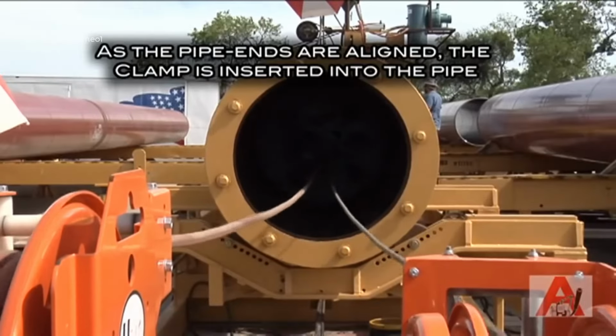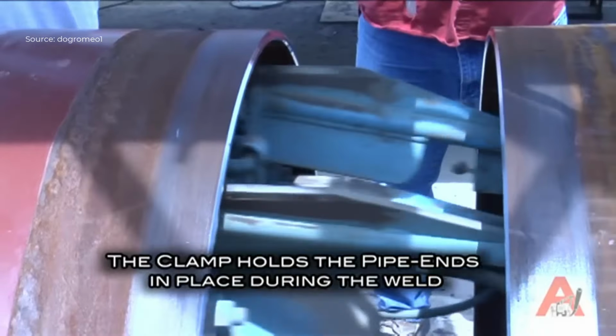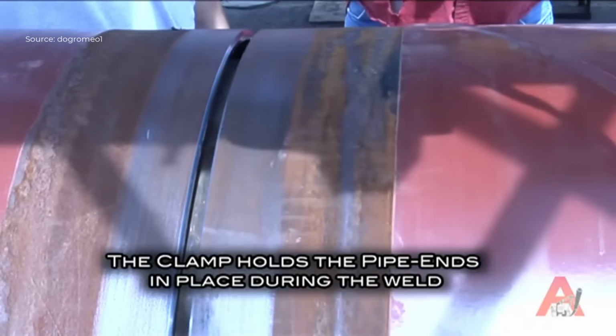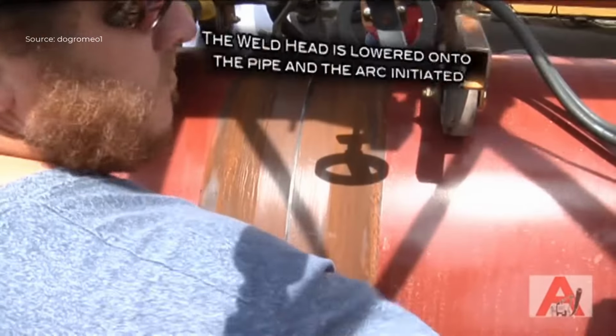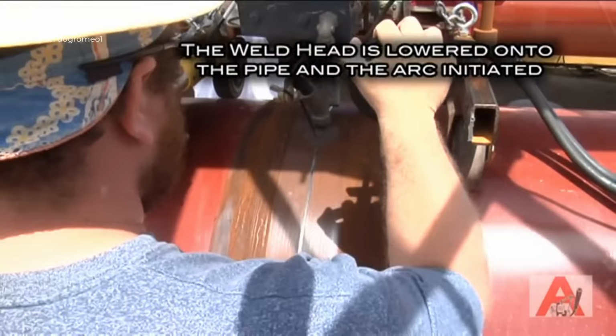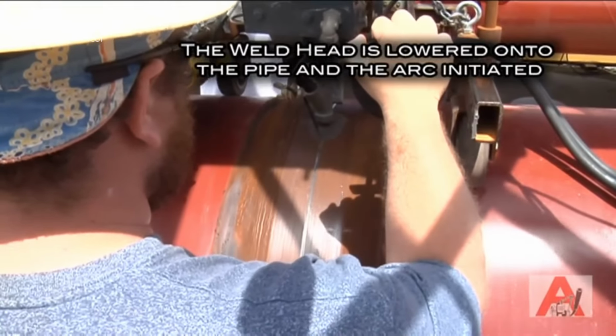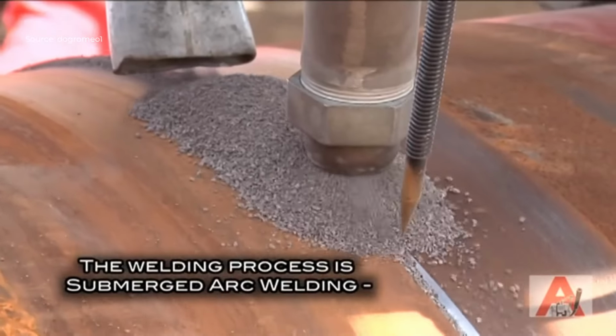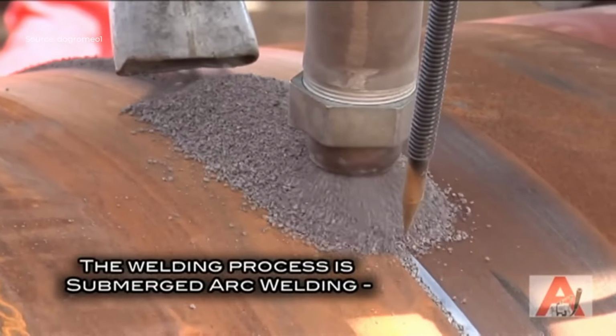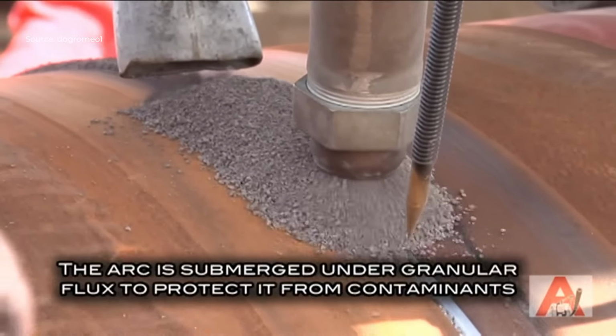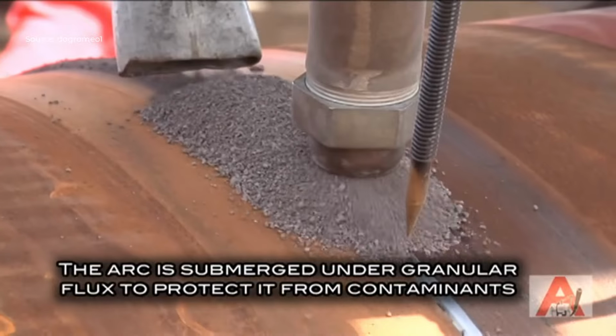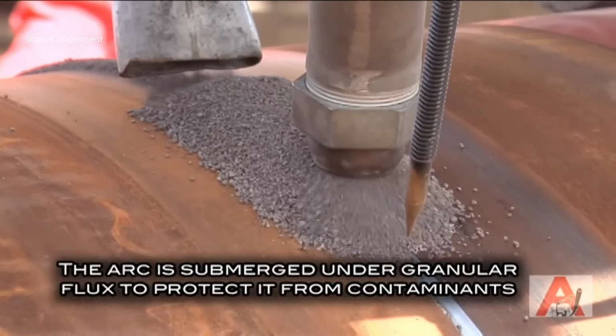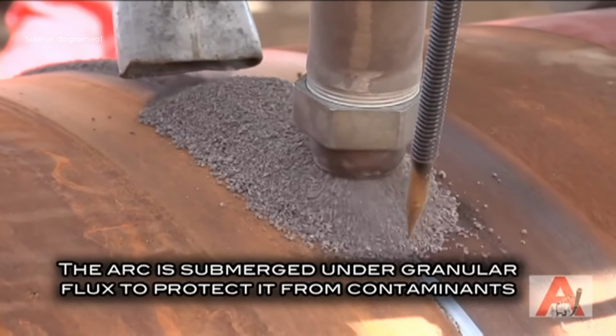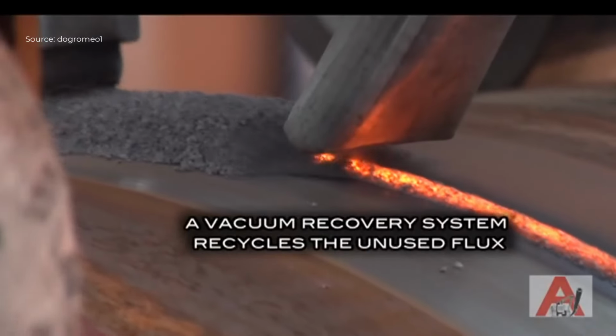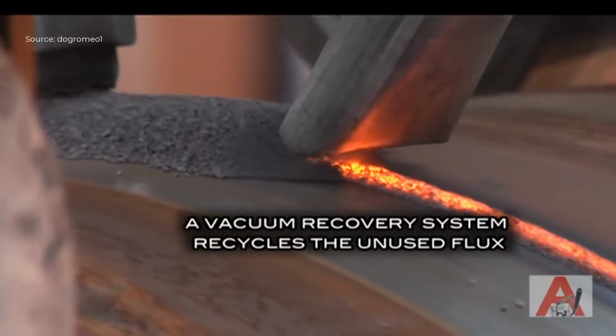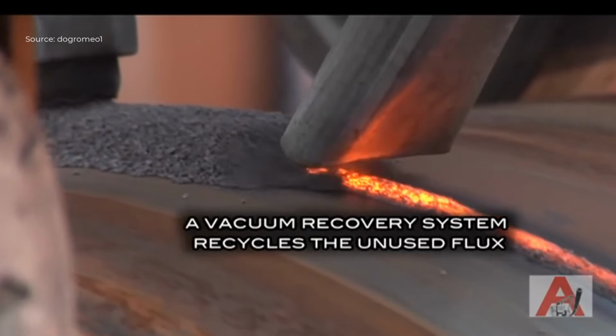At the outside diameter 1 welding station, 2 pipes are rolled into position. A spacer ensures the correct alignment of the pipe ends, while an internal clamp is inserted to hold them securely in place during welding. The weld head is then lowered onto the pipe, and the submerged arc welding process begins. In this technique, the arc burns beneath a blanket of granular flux that protects the molten weld pool from oxygen and contaminants. A vacuum recovery system collects and recycles the unused flux for future use.